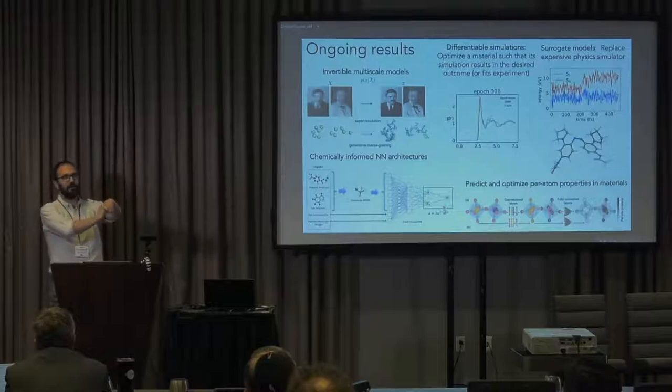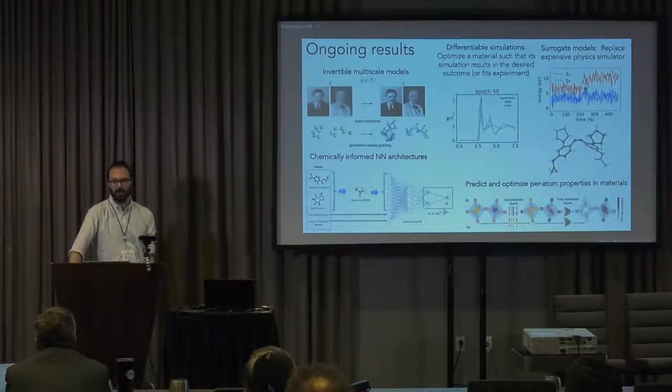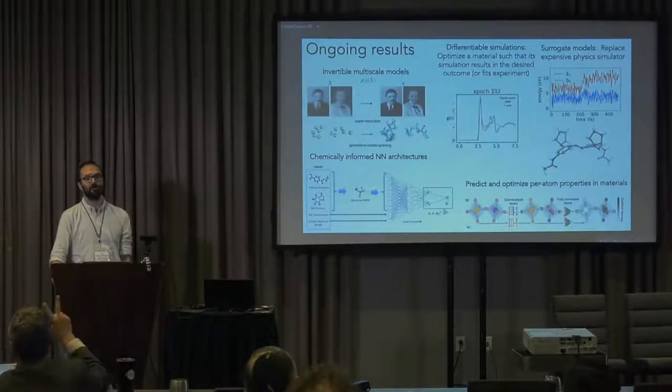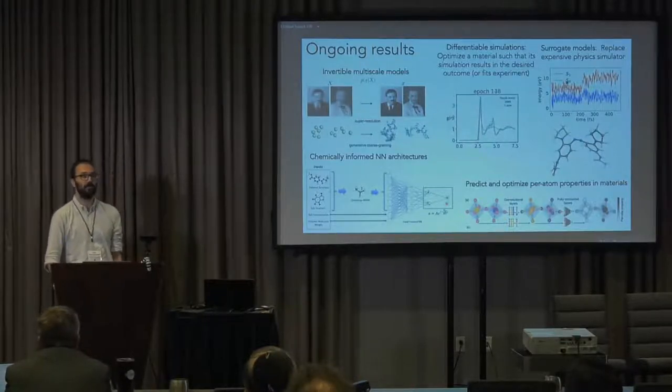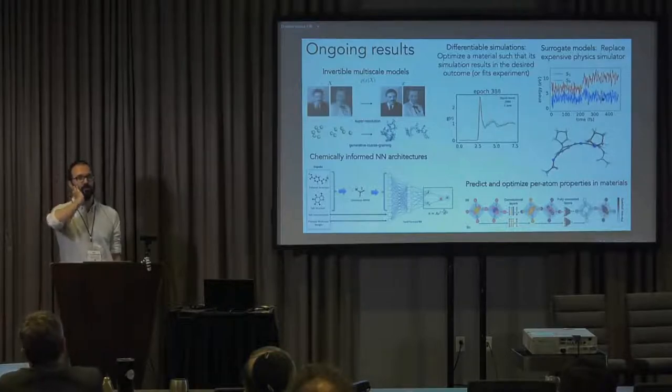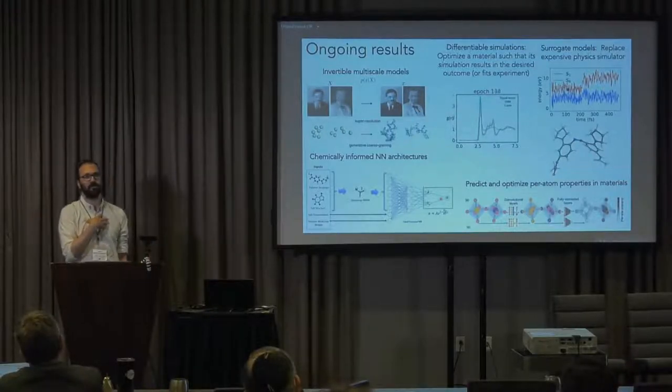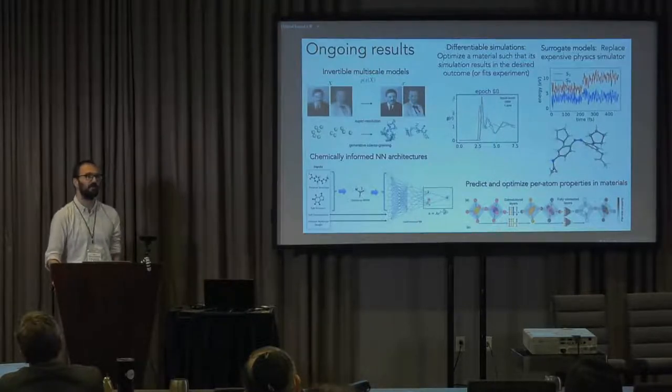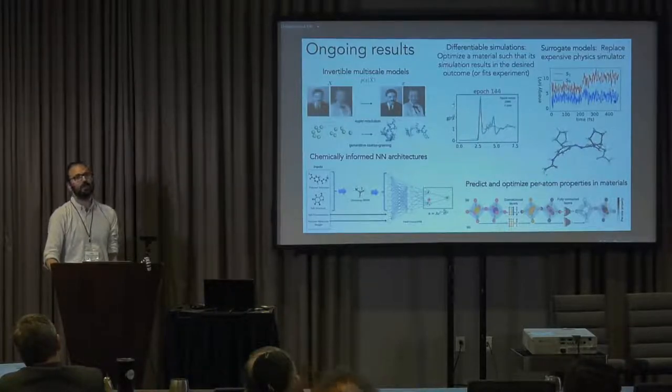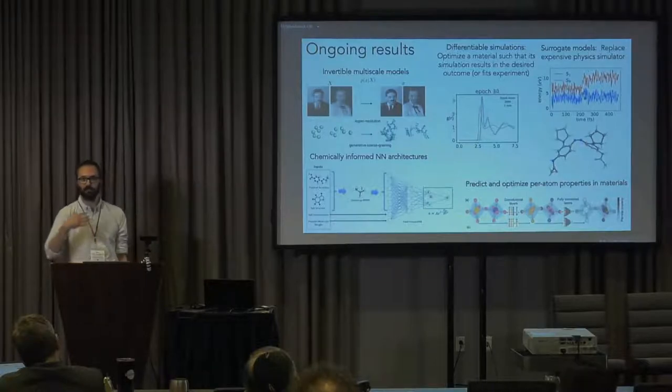And this is too cheesy, but I think there is a lot more here and I'd love to hear from the audience. In embedding the structure of problems into the neural network architecture. So this is a cheap shot at it. We know the system we're interested in follows an Arrhenius law. It has a temperature dependence that we know. So instead of training a black box model that given a chemical structure produces the property we care about, which in this case is polymer conductivity to make batteries, we say, well, we know from known experiments so far that polymers conductivity follows an Arrhenius law. So we want to embed that known behavior on top of the black box. We don't know how structure becomes conductivity. We're going to throw that at the machine learning model. But we do know how the conductivity varies with temperature. So how do we get to leverage the known structure of the problem? And this structure is trivial. This is a very easy example. But how do we embed the structure of the problem into the learning architecture that we're using, such that we don't need to waste all our data learning the one relationship that we knew already, which has these simple terms.